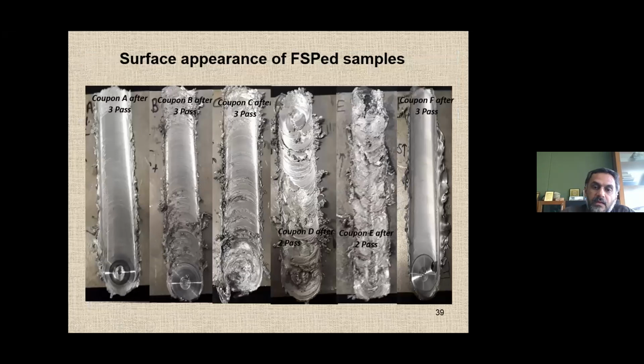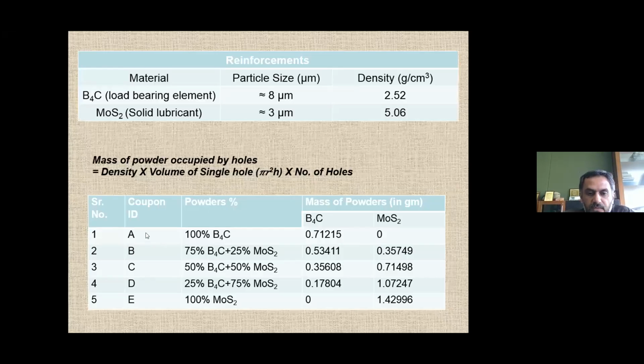You please understand, whatever parameters were optimized in the previous case, right? In case study 1, what we found in the previous study is that 3 passes with change in direction was the best, and the hole method was also best. So we consider that as a condition, right? Now we didn't vary the hole method, slot method, or without FSP. We just started with one particular system, which is your hole method, which has the best wear resistance, and the 3 passes with the change in direction. And then all these compositions, starting from 100% B4C to 100% MoS2, were tried, right?